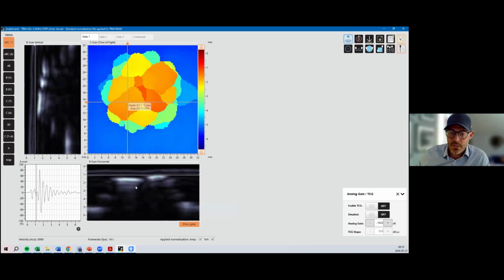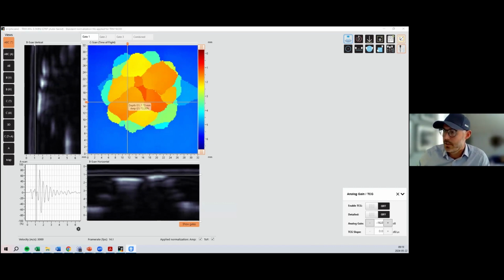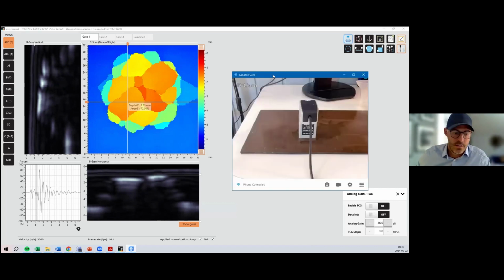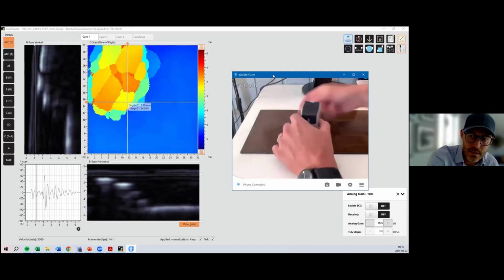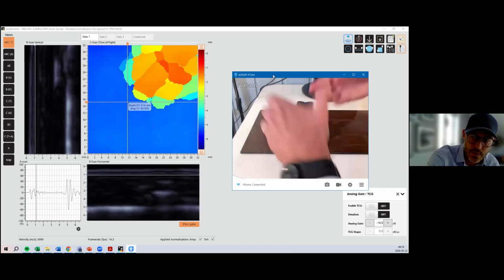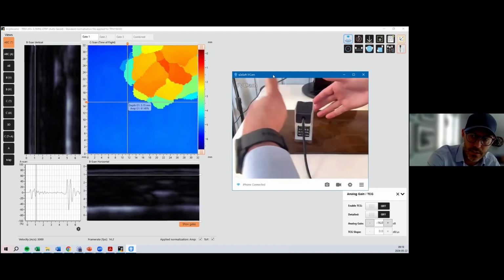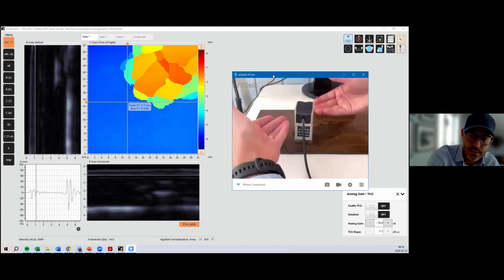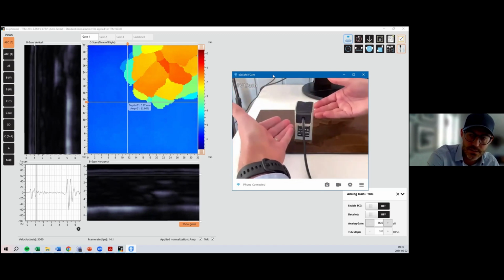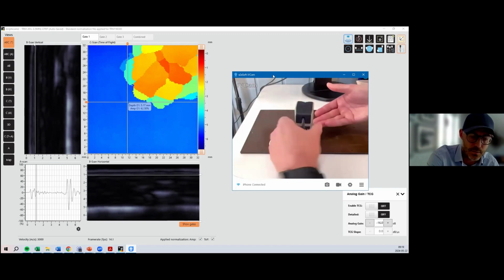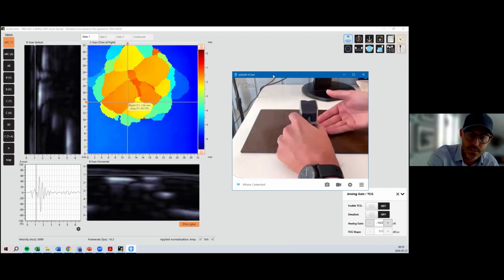So what has happened here is that this has been impacted, and then you're pushing down the carbon fiber and then it releases back up. But then the adhesive has released, so you actually have air pockets inside there. It's what we call an impact damage. So this must be repaired.